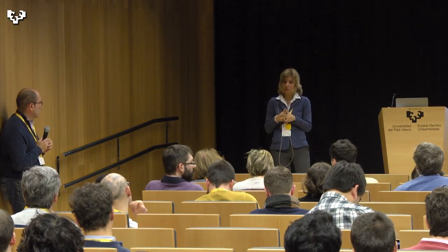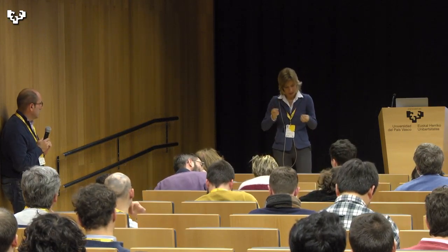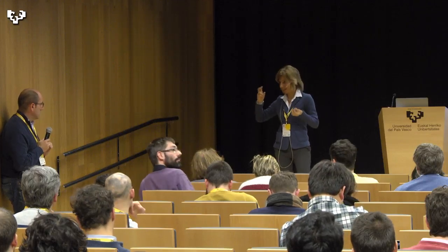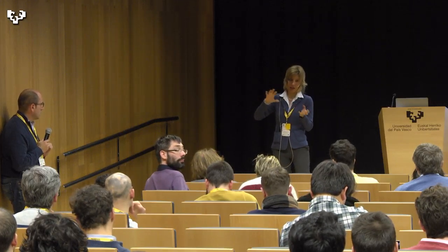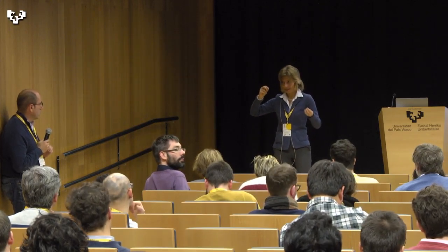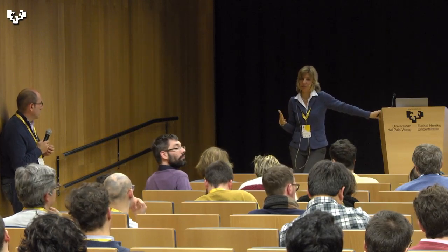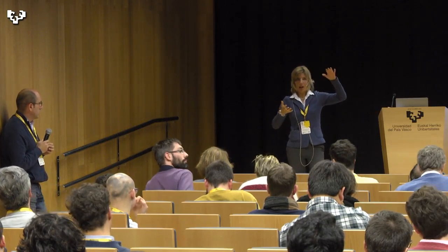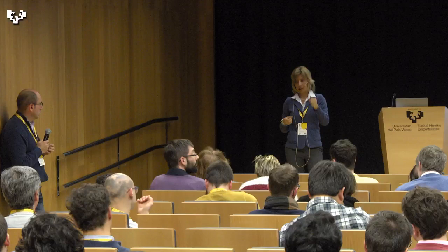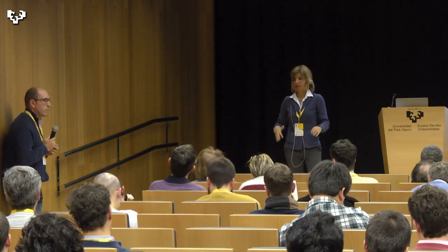Let's say we vary J from 0.6 to 1.3 in this energy range, and also U, let's say from 0 to 4, I think. So we didn't go to extremely high values, but as I said, the J's are very solid, and you always see a strong ferromagnetic J1 and a strong antiferromagnetic J3, always.